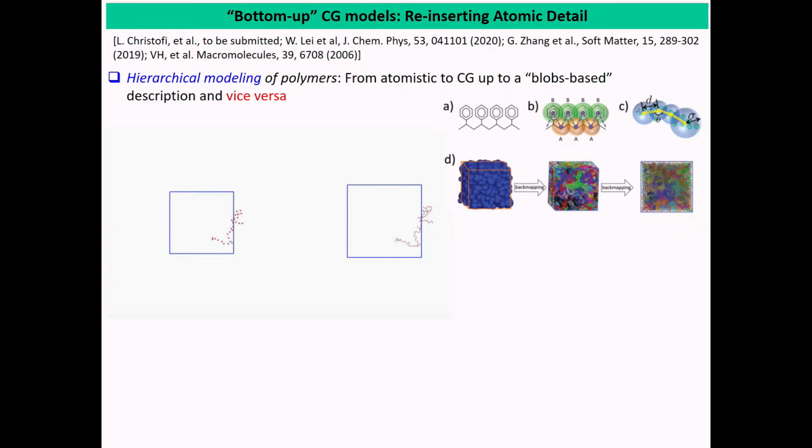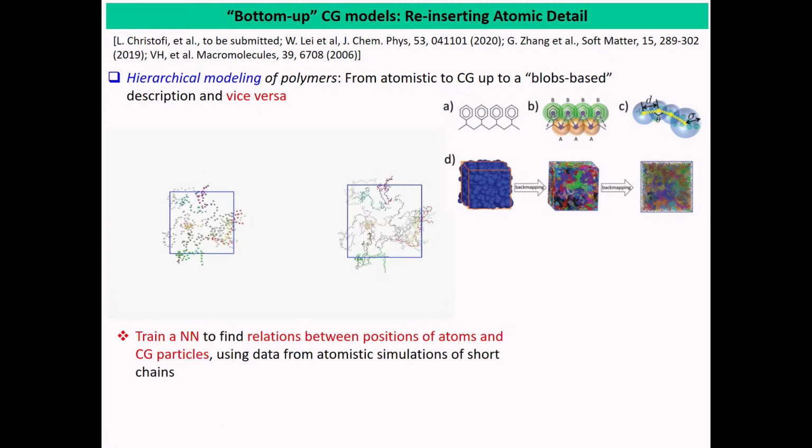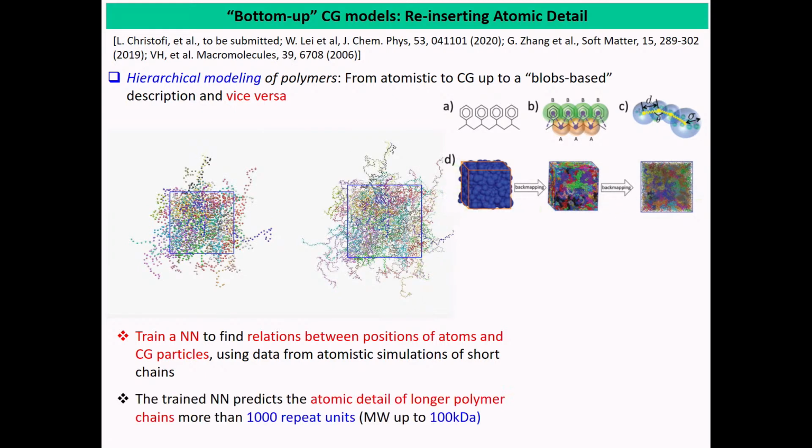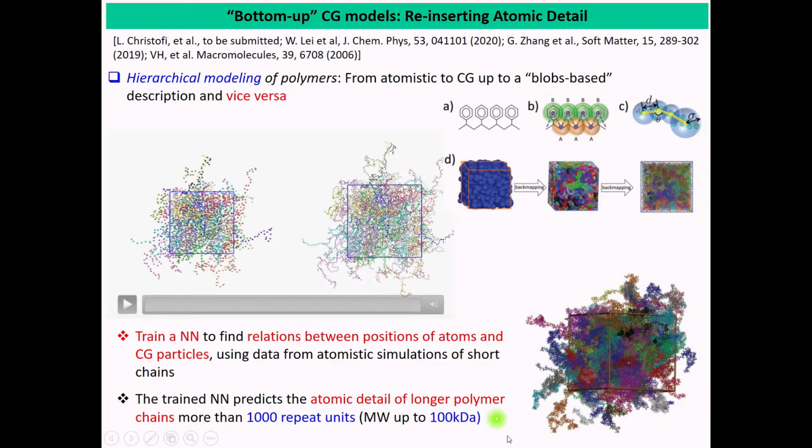And what we also need, and that's very important, is a way numerically to go backwards. So to go not only from the more detailed to the less detailed picture, but also, if possible, to introduce detail in the less detailed mesoscopic models. The reason is very simple. Quite often, we have experimental data, or we want predictions in the atomic level. So it's very desirable, if possible, to go backwards. And there are ways to go backwards: there are geometric techniques or machine learning, a new method where we use neural networks to solve the backward problem, which is this back map mentioned here.